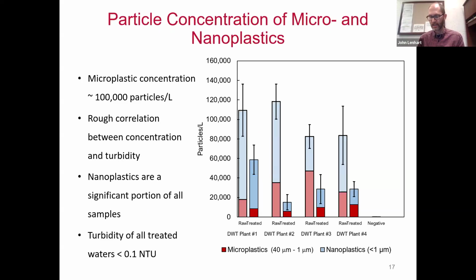All right, let's get to some results. Again, we've collected treated and raw water from 4 different plants. These results are summarized here. On our y-axis we have concentrations of our particles in terms of particles per liter. We have our 4 different plants on the bottom, and then our control over here. So we're looking at raw water and treated water. The blue is the portion that are nanoplastics, so these are plastics that we've identified as having a size less than 1 micron. The red is the microplastics, which for us is particles between 40 and 1 micron. We did not identify any particles greater than 40 microns in any of our samples.